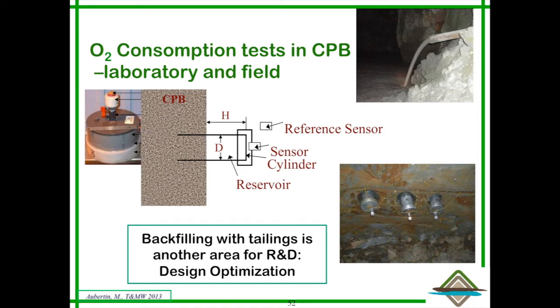What this has shown is that except for the external layer, there is very little oxidation. In fact, the backfill remains stable for a very long time, even along exposed faces. This means that if you have a proper mixture, a proper recipe with the proper binder, you can use your reactive tailings as backfill underground.